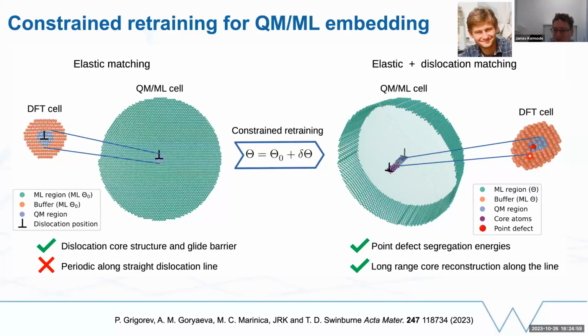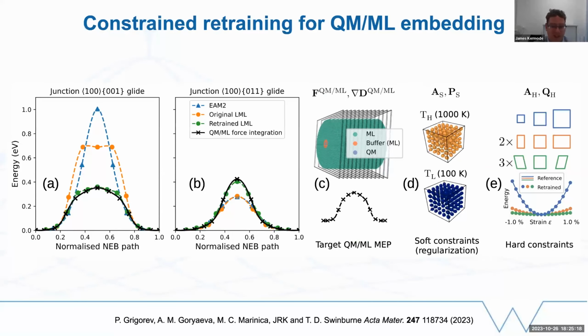We could put additional defects, vacancies, or hydrogen or helium impurities close to the dislocation line and study that additional chemistry with localized quantum mechanical precision while using an interatomic potential for the rest of the dislocation line. So how did we do that? In a bit more detail, it was, as I say, a constrained retraining of the machine learning potential. And we did that using 3 different ingredients.